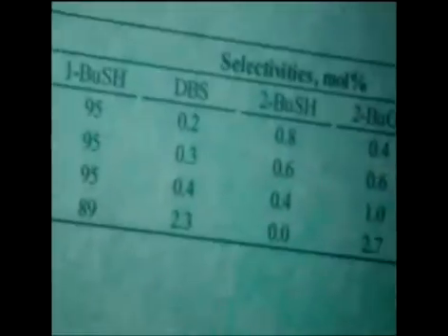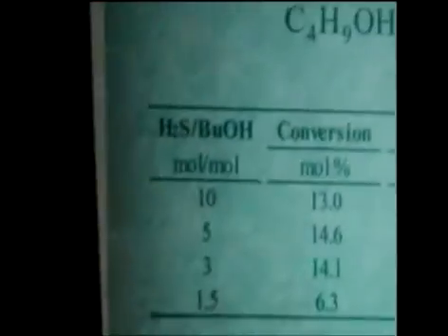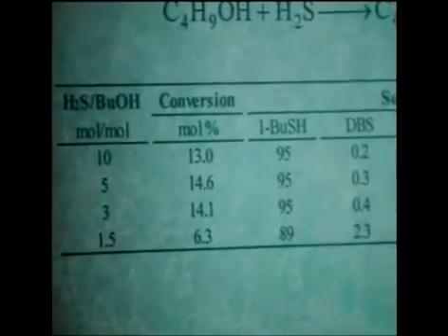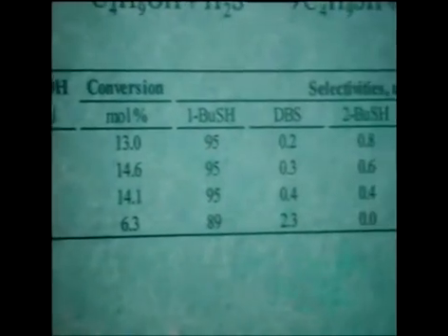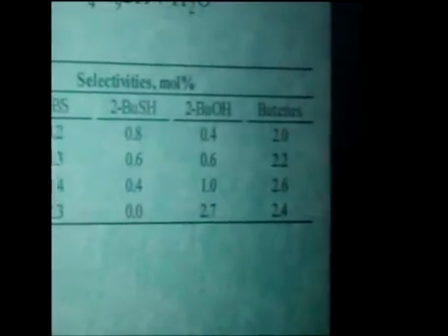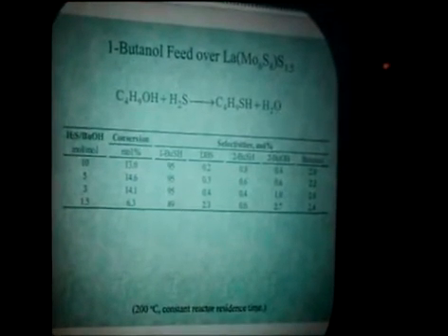Well, that takes care of our methane thiol, and I have one slide to tantalize you with our more recent results with butanol. Turns out we can eliminate the carbon oxide, carbonyl sulfide, and carbon disulfide. There are no analogs to those compounds in the C2, C3, C4 alcohol game. So what we do is just use a higher alcohol, and I was able to obtain pretty high selectivities to the primary butane thiol, and again, fairly low ratios of hydrogen sulfide to butanol. So I still think these are pretty promising catalysts for thiol synthesis. This is starting to get very close to the most recent patented selectivities.